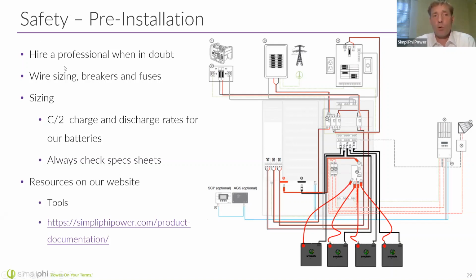Now these batteries can all surge, and they can surge to a rate of C, but we only do that for about 10 minutes. We limit that because as you're surging a battery and discharging it really rapidly, you're generating some heat inside the cell. And so as the temperature of that cell builds up, we then stop to prevent damage to the cell and for the greatest longevity of the battery.